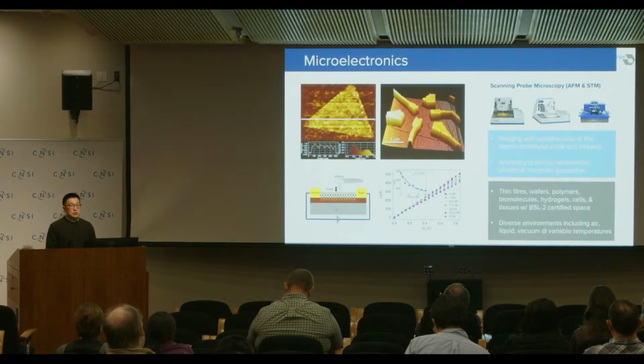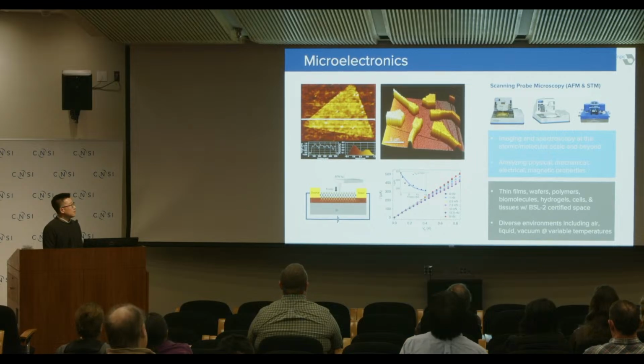So I would like to introduce 3 practical examples of how we can support your research using the equipment at NPC. The first example is microelectronics. So here is an example of the sample, a single layer of molybdenum disulfide. By utilizing the SPM or AFM, you can analyze the shape of the sample, which shows triangle shapes. Also measure the thickness of the thin film, showing around 7.5 angstroms.